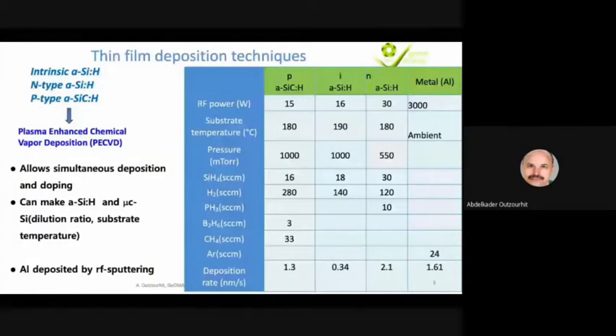Okay, so this slide here gives you the deposition condition parameters that we used to deposit the various thin films. The intrinsic hydrogenated amorphous silicon, the N-type hydrogenated amorphous silicon, and also the hydrogenated amorphous silicon carbide thin films were all deposited by plasma-enhanced chemical vapor deposition, PECVD. This technique allows both simultaneous deposition and doping of the films by just changing the gas mixture that we used during the deposition. In addition, this technique also enables us to make either amorphous silicon or microcrystalline and nanocrystalline silicon, just by changing the composition of the precursor gases within the deposition chamber.